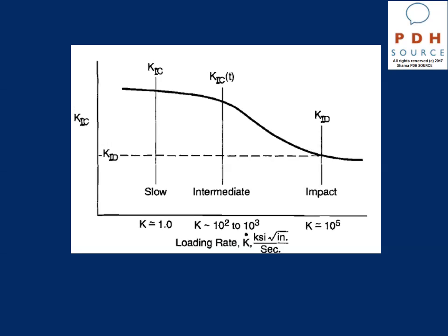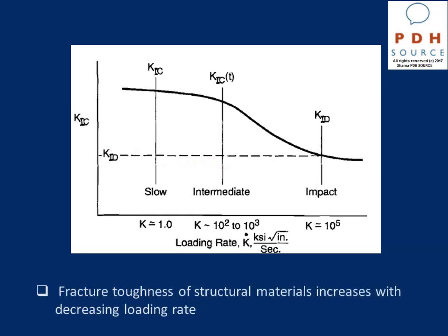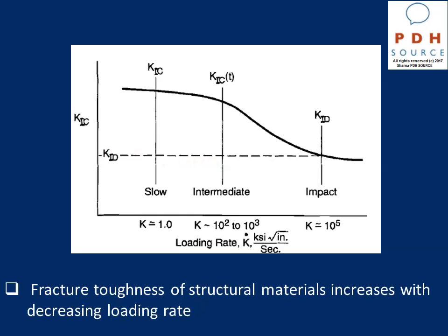This figure shows that at constant temperature, fracture toughness tests conducted at higher load rates generally result in lower fracture toughness. So accordingly, we can say that fracture toughness of structural materials increases with decreasing loading rate.